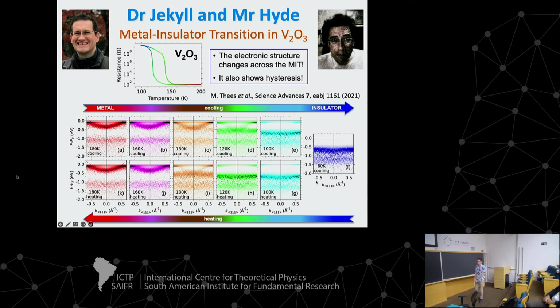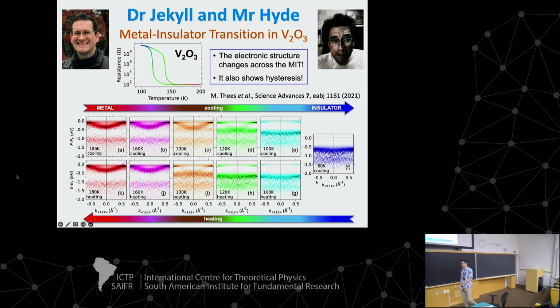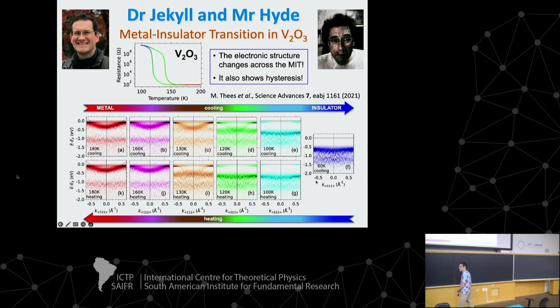But one answer that you can give to that is that the electron-electron interaction is of the order of the electron volt, and the temperature is 2 orders of magnitude smaller. So you do not expect those things to happen. So that's why the correlated electron problem is so hard. It happens at an energy scale much smaller. Room temperature is 25 millielectron volts. So if you go from room temperature to 0, indeed you will be changing the energy scale by only 30 millivolts, whereas electron-electron interactions are of the order of 1 electron volt.